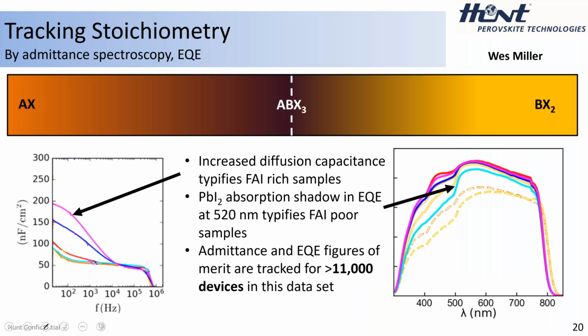So we've been able to link perovskite stoichiometry to durability. Now, this may sound like a bulk attribute, but in reality, I think this is a surface attribute, because even when you modify the perovskite's stoichiometry, quote unquote, it still functions as a solar cell. So the bulk, the internal, like the Tootsie Pop, the caramel center is still caramel, right? We're not really affecting it. It's the crunchy outside candy that we're affecting. And so when we say we're losing FAI, where are we losing it from? Not from the middle, we're losing it from the outside. So again, this is why I think perovskite stoichiometry is more of a surface property, grain boundary property, than that of a bulk within our context here.